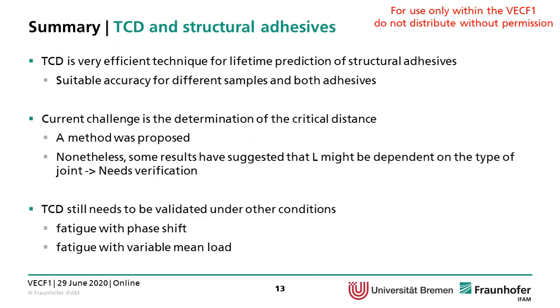Now to summarize some of the results that we had here regarding the use of TCD for structural adhesives. TCD is a very efficient technique for lifetime prediction of structural adhesives. We had a very good accuracy for different types of samples and both types of adhesives. However, the current challenge is the determination of the critical distance. A method was proposed here. Nonetheless, some results have suggested that the critical distance might be dependent on the type of joint. So for other projects that we used, this still needs verification, and the TCD still needs to be validated under other conditions, for instance, fatigue with phase shift, fatigue with variable mean load, and so on.